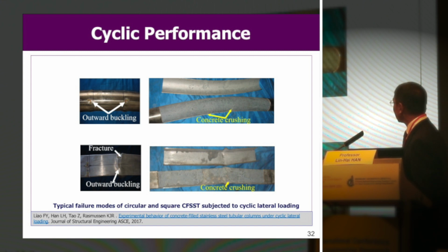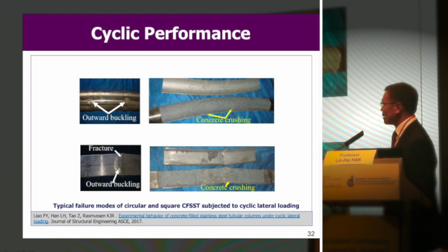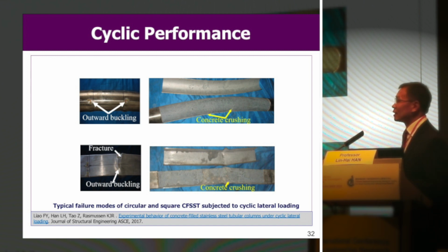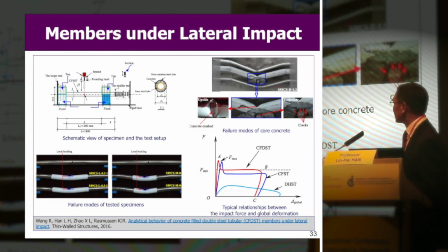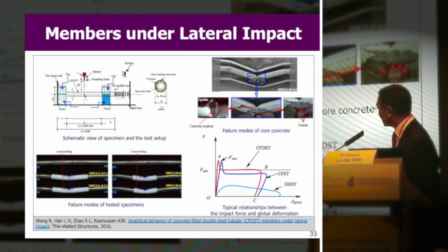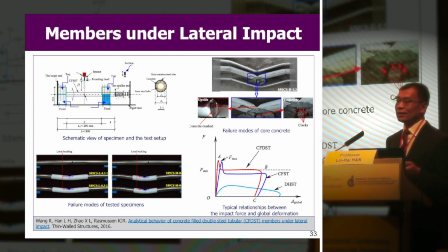We check the concrete surface. You can see the concrete and the steel tube can work very well. So the concrete can keep integrated during the loading process, even after failure. Under lateral impact, you can see again, we remove the outer stainless steel tube. You can see the core concrete still keeps well, though there is a very large deformation of the specimen.